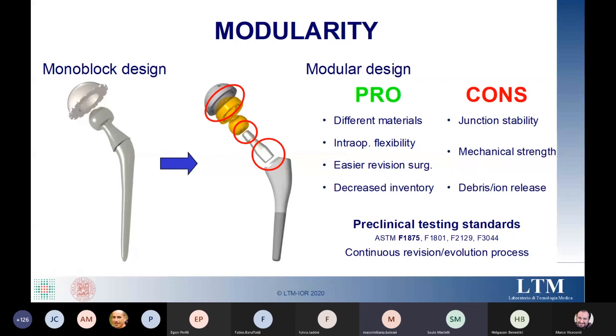However, on the other hand, you also have concerns which now become an issue, for example, junction stability, the mechanical strength of the junction itself, generation of ions and debris, which can be responsible for adverse tissue reaction. These have been cited continuously in the literature since the introduction of modular designs. Now, over time, standards concerning issues around corrosion of metallic implants have been introduced and became available. The first one listed, the ASTM F1875, contains a recommendation for fatigue corrosion testing of head-neck junction.